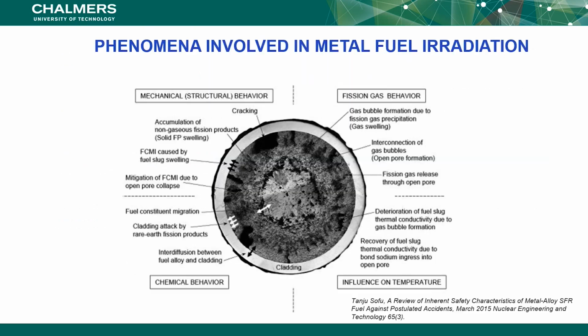Next, please. So if you look at how the nuclear fuel can look after a certain time in the reactor, you see that it's not a compact material anymore. It has a lot of damage. It has a lot of different phases which are forming, and you see the cladding is already in contact with the fuel. So then you can think that a lot of chemistry is happening there as well.